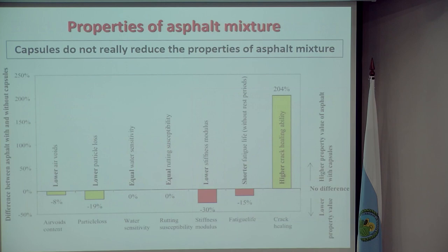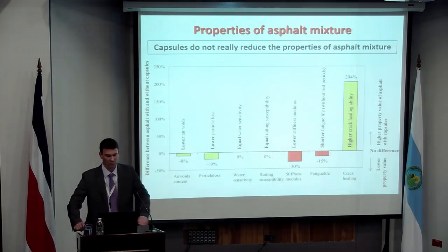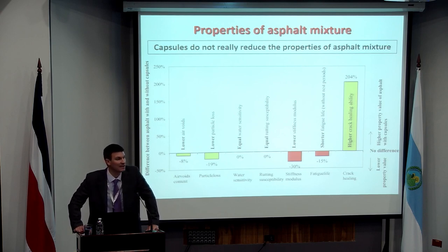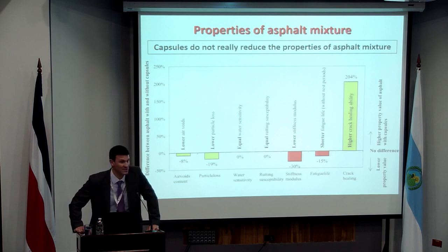What does it do to the material? Because this was a concern that the asphalt producers had: you're adding a material now that's going to cost money. It potentially will allow our material to self-heal, but what does it do to its other properties, particularly early on in the life? And there are subtle differences. It is slightly lower stiffness, so you'll see there's about a 30% reduction in stiffness because of those capsules that initially break during the production process. They will release that low viscosity fluid and inevitably they will have an effect. But the other properties aren't that different. And so we are fairly comfortable that if this is done correctly, we can end up with a material that is effectively a self-healing material.